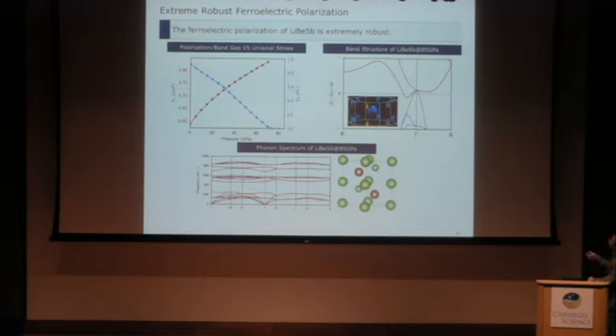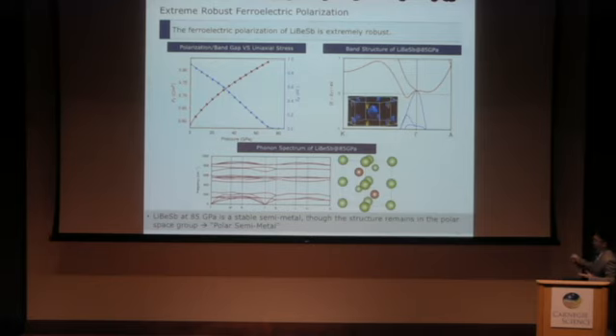And this is the band structure. Indeed, at 85 gigapascal, there are some bands crossing the Fermi level. But what's surprising is even at this very high pressure, 85 gigapascal, the structure remains in a polar space group. So we look at the phonon spectrum, and all the phonon branches are stable. So that's why I call this a high pressure polar semi-metal.